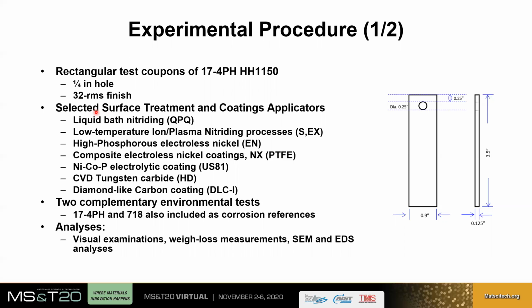So among these surface treatments, essentially we had nitriding, 2 types of processes, the QPQ process, which is liquid bath, and some higher nitriding process from 2 different vendors. Then we had a number of plating processes, electroless nickel with PTFE, which gives self-lubrication, as well as an aerospace nanostructured nickel cobalt phosphorus coating. We also had a CVD tungsten carbide coating and a DLC coating for comparison purposes.